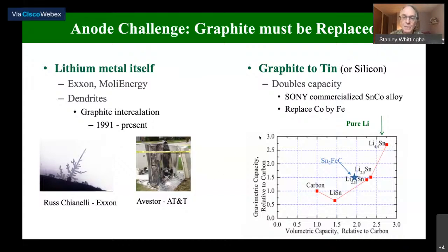So we had a research project to, in fact, replace graphite. We chose tin to do that with. It can double the capacity. If you see at the bottom here, this is carbon. This is gravimetric, volumetric, and we put carbon at 1. So you can see if we use tin, we can double the volumetric capacity. With just 2 lithiums, we gain a bit more by going to 4 lithiums, and it increases the gravimetric capacity a little bit as well.